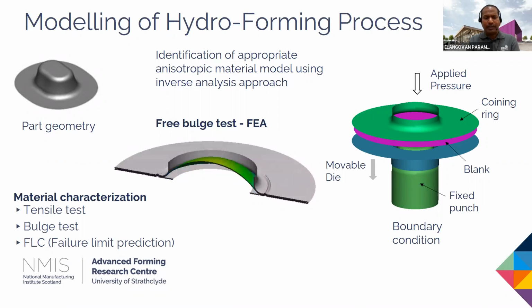And then the forming limit curve, it's mainly to assess the failure limit of the material during the process. And we follow some specific approach in order to identify an appropriate anisotropic model using an inverse FE approach. So there is an example you could see in the animation. So we try to simulate virtually and then try to identify an appropriate anisotropic model.